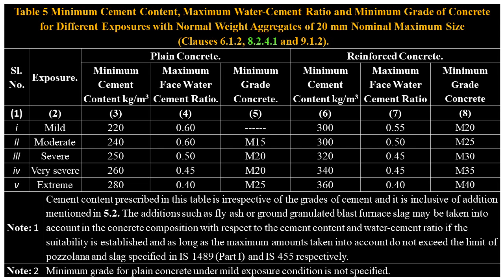And for reinforced concrete, minimum cement content 300 kilograms per cubic meter. Maximum free water to cement ratio, 0.55, grade of concrete, M20. Serial number 2. Exposure, moderate. Plain concrete, minimum cement content 240 kilograms per cubic meter. Maximum free water to cement ratio, 0.6, grade of concrete, M15. And for reinforced concrete, minimum cement content 300 kilograms per cubic meter. Maximum free water to cement ratio, 0.5, grade of concrete,